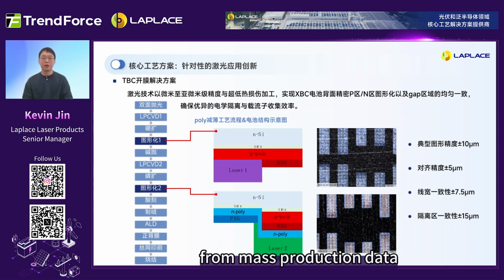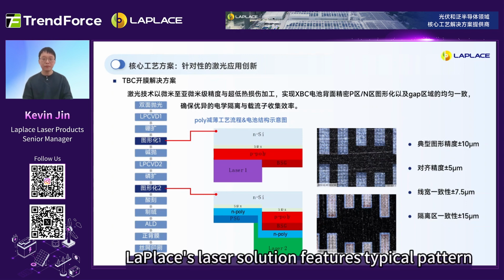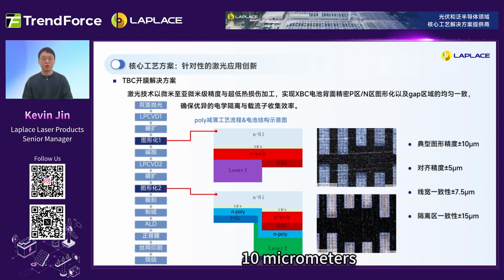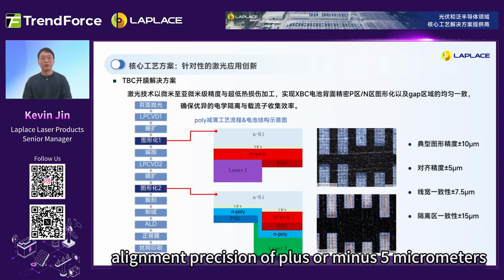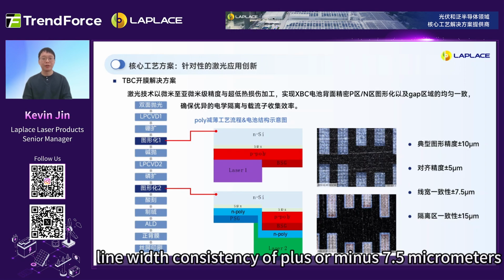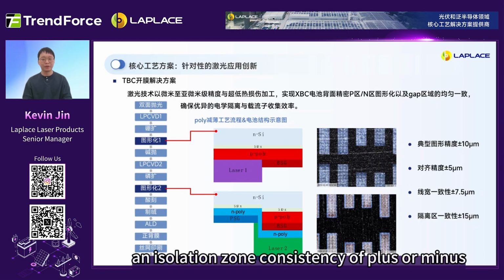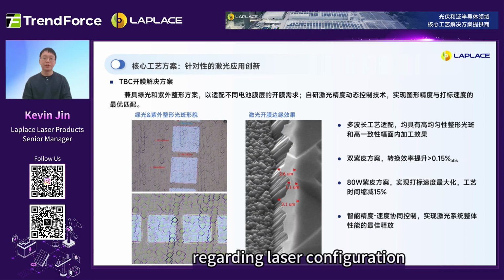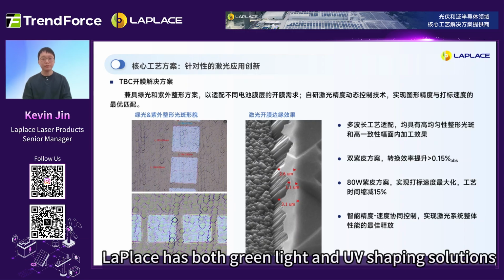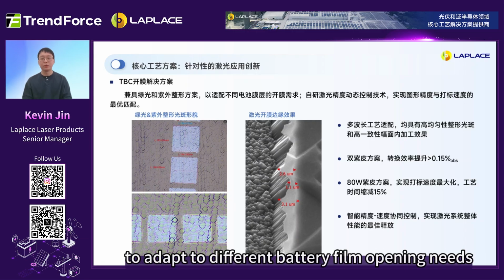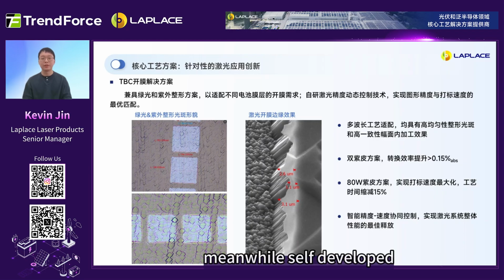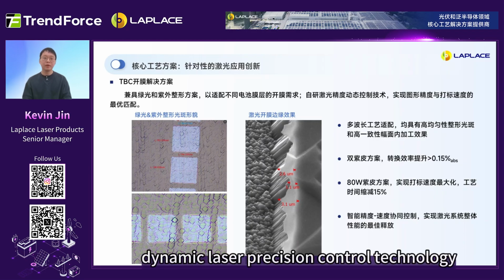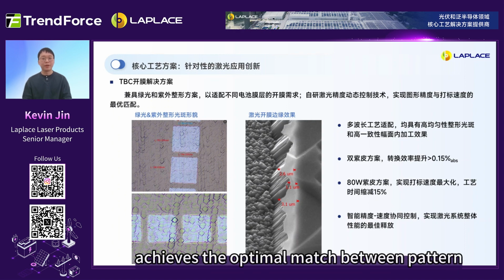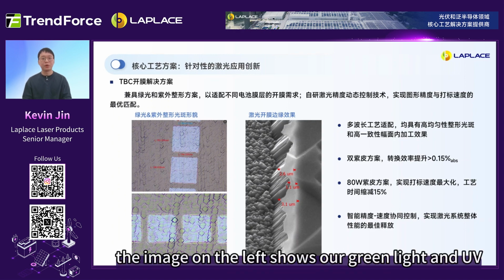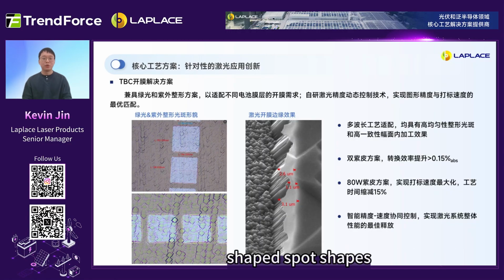From mass production data, Laplace's laser solution features typical pattern precision of plus or minus 10 micrometers, alignment precision of plus or minus 5 micrometers, line width consistency of plus or minus 7.5 micrometers, and isolation zone consistency of plus or minus 15 micrometers. Regarding laser configuration, Laplace has both green light and UV shaping solutions to adapt to different battery film opening needs. Meanwhile, self-developed dynamic laser precision control technology achieves the optimal match between pattern, precision, and marking speed. The image on the left shows our green light and UV shape spot shapes.